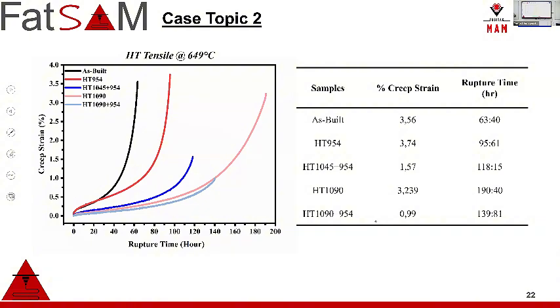In my case, why I like less plastic deformation, because the temperature 649 is service condition temperature, but the applied load for the creep test is 650 megapascal. You will never use it in 650 megapascal. With safety coefficients, the maximum applied load is around 360 megapascal or 375 megapascal. So less plastic deformation means you are in safer conditions, no plastic deformation.